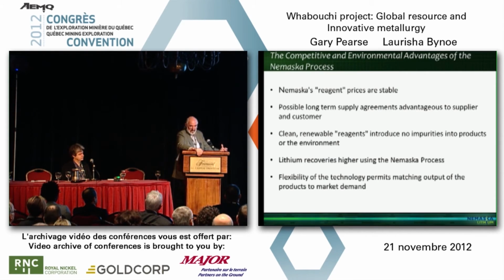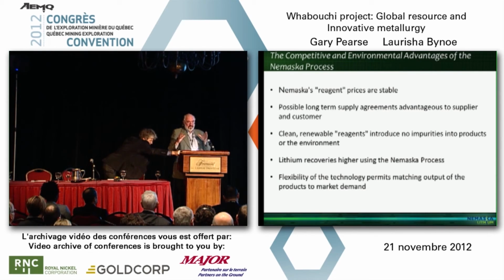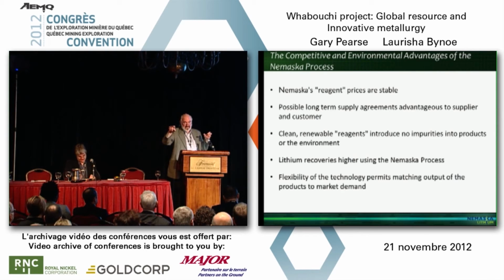For the one thing, we can take that waste solution from the lithium hydroxide monohydrate crystallization, which is 25% of the material, and we can put it then through our lithium carbonate circuit, and it's essentially free feed. Otherwise, it's a waste product that is a bit of a nuisance to get rid of. And we're able to convert 97.3% of that waste into very high purity lithium carbonate. And this gives us much higher recoveries. And the flexibility of the technology is such that we can reduce the lithium hydroxide monohydrate production and direct more lithium hydroxide to the lithium carbonate circuit, and we can balance the thing to fit the market for the two major products in the market.